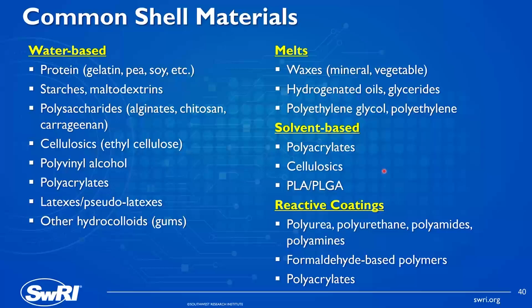Some solvent-borne polymers, some of the common ones there, especially for biodegradable systems, polylactic acid or polylactic-co-glycolic acid, used a lot in pharmaceuticals. Some of the cellulosics, especially ethylcellulose, is more solvent-borne. And then reactive coatings. So these are going to be shell materials where we're using the chemistry to make the shell. So you're emulsifying into a mixture of monomers to make either polyurea, polyurethanes, polyamides, or formaldehyde polymers, or even some acrylate-based systems. And this is where there's been a lot of recent creativity for making biodegradable shell materials, because that is a big emphasis, given an upcoming ban on microplastics in the EU.